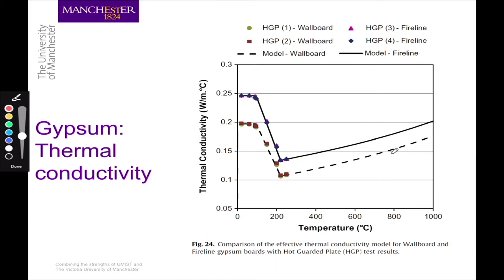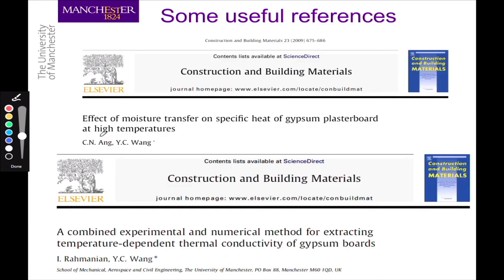There are different schools of thought about why this happens. We think it is because of thermal radiation inside the bubbles. There are a lot of bubbles, voids inside gypsum. As temperature increases, radiation becomes really important, and that's why it's increasing. So we carried out a detailed research program to quantify these effects, and these are our prediction lines, and these dots are our experiments, and they seem to be quite good. Again, we have published a few papers, and these are sources of information which you might be interested in reading about.